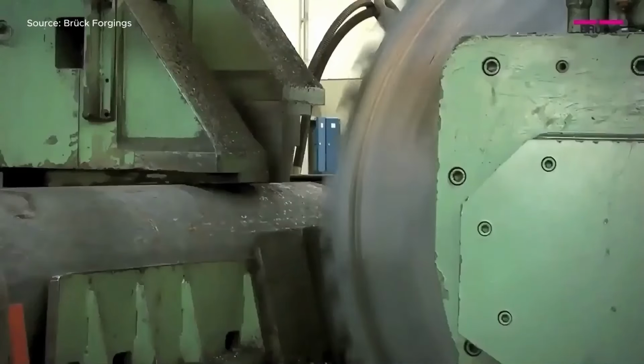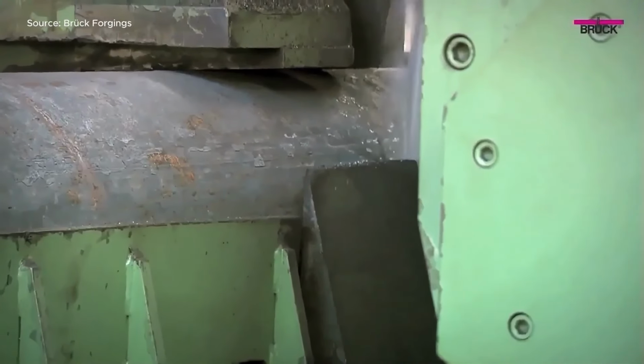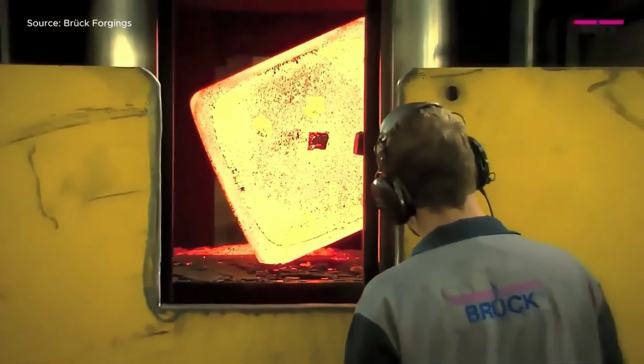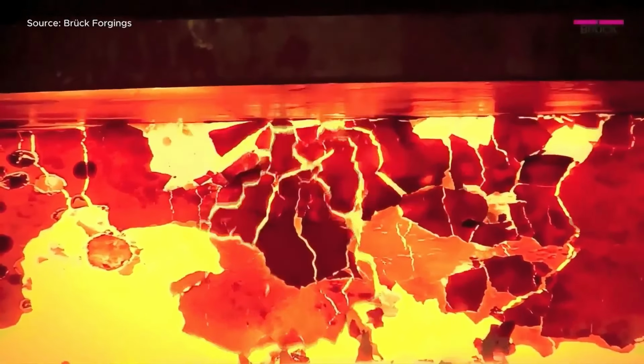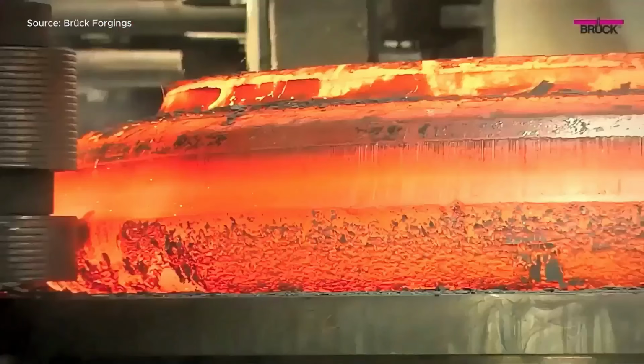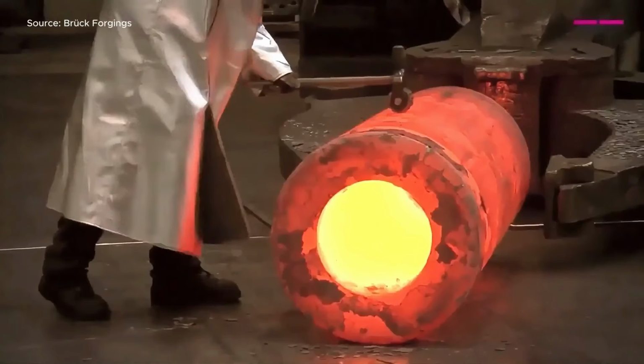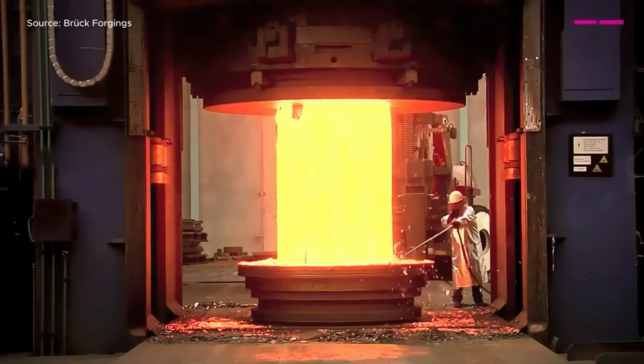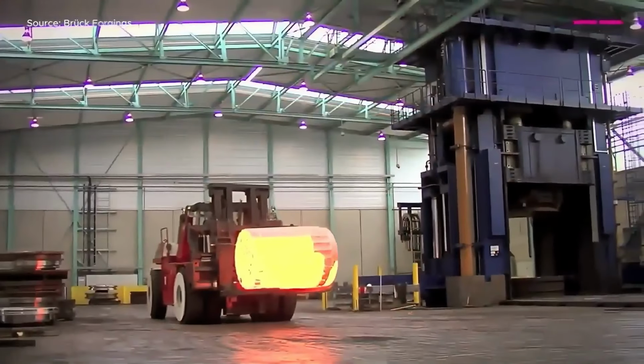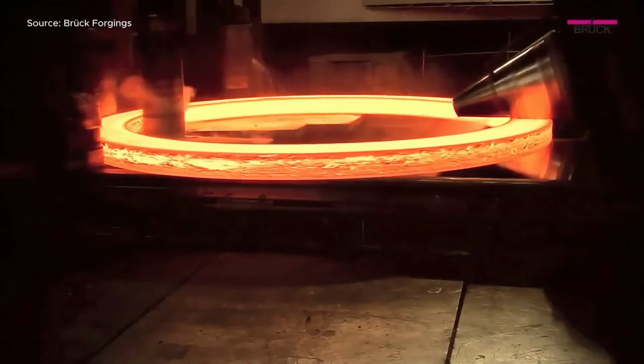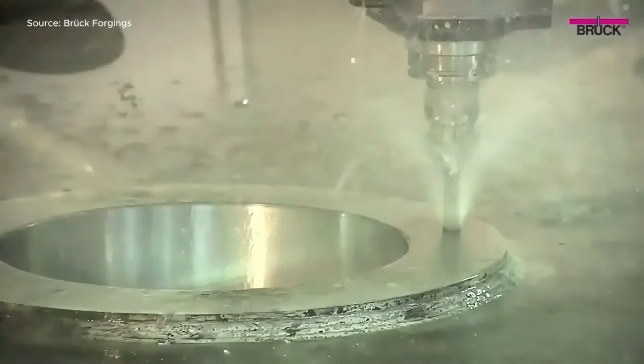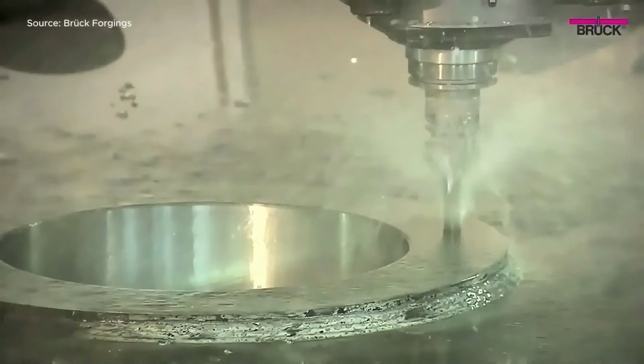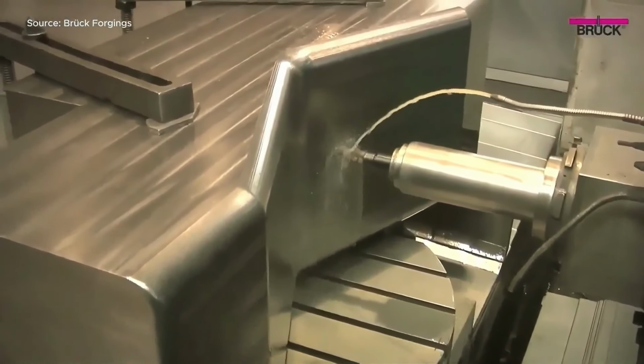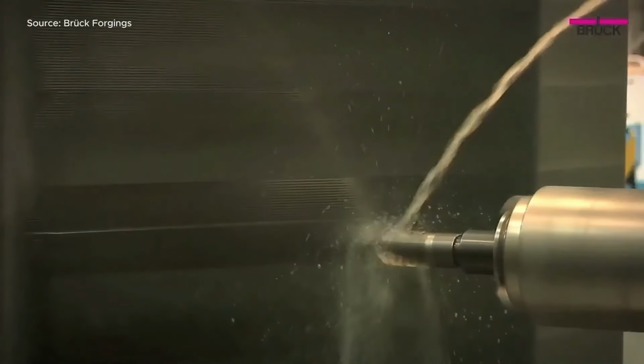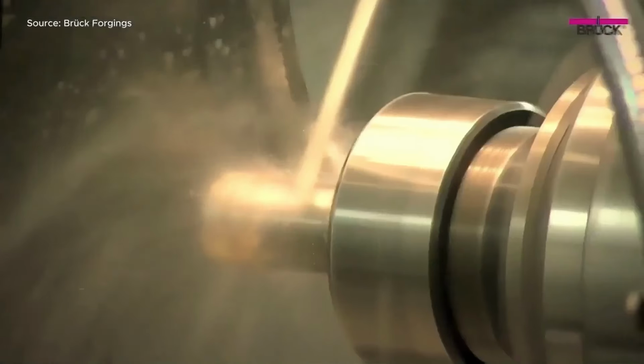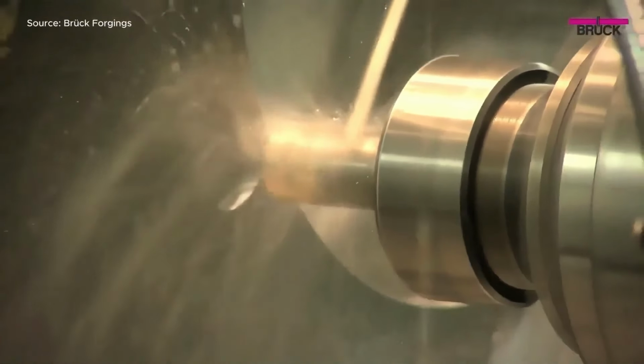Bruck, located in Saarbrücken, Germany, specializes in the production of seamless hot-rolled rings, flanges, and custom-forged parts. Their seamless rings range from 300 mm to 6,400 mm in diameter and can reach heights of up to 1,600 mm, with radial widths up to 1,000 mm and piece weights up to 40 tons. The company also manufactures forged parts with dimensions up to 4,500 mm by 4,500 mm by 10,000 mm, and piece weights up to 50 tons.